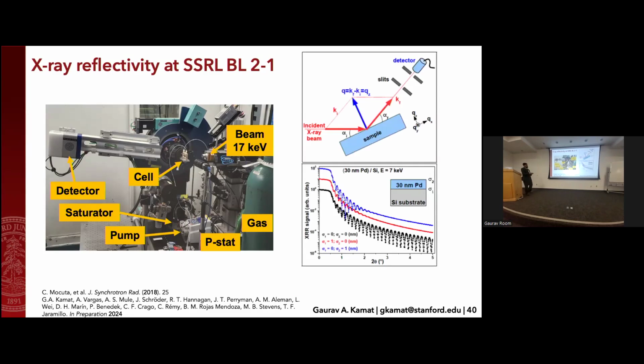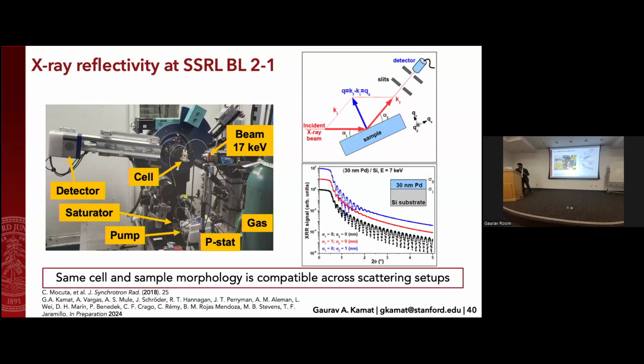And X-ray reflectivity data is a little bit weird. It looks something like this because this is what your setup is looking like. Your incident X-ray beam is reflecting off of your sample. And if there's multiple layers in your sample, they're going to interfere with each other on the way out, the light waves are. And so if you have a perfectly smooth surface, you're going to have this very, very, very bumpy signal because of the constructive and destructive interactions. But if you have even slight levels of roughness anywhere on your surface, you'll see those bumps, but then they'll start to damp out.